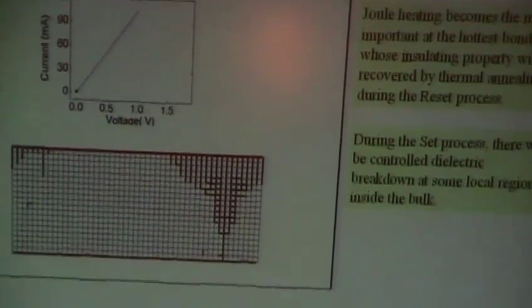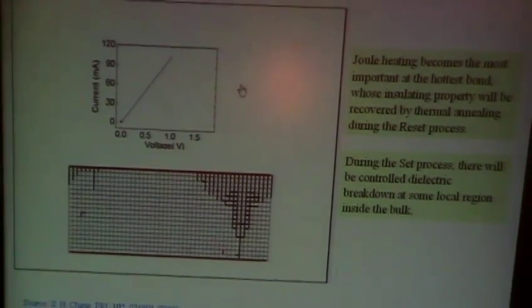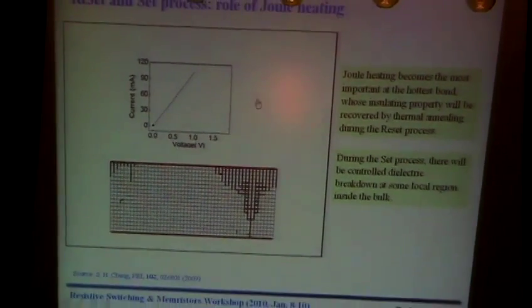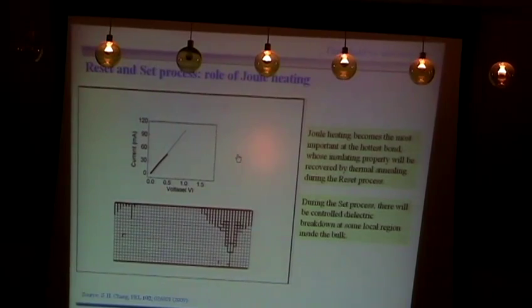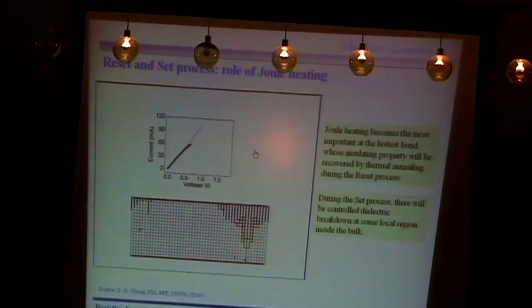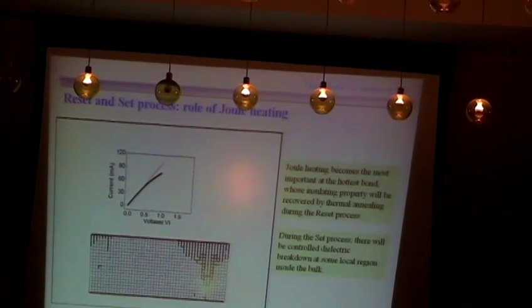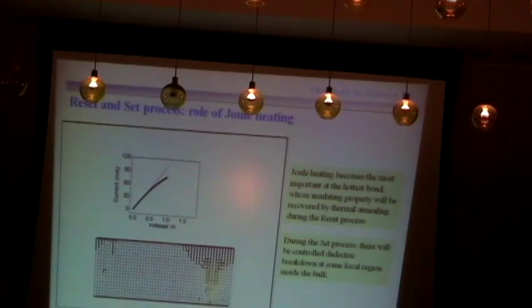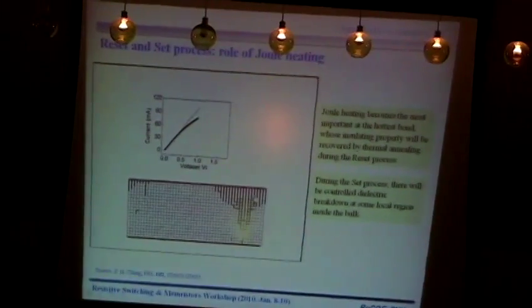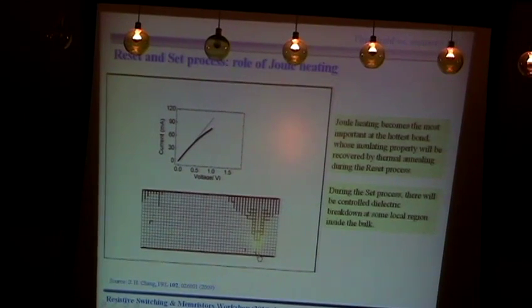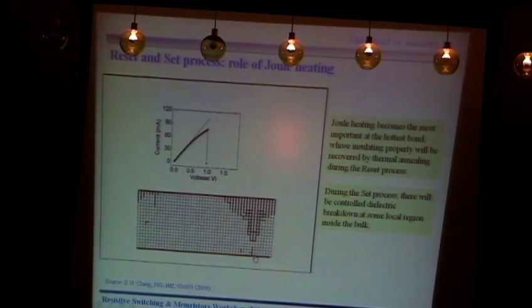So it is a kind of self-organized evolution process. That is the forming process. Then the reset and set process. Here we put in the Joule heating effect. As we put through more current, the temperature will rise. This region will get hotter than the other regions because most of the current goes through this hottest one. Then suddenly it will break down, so it will change into the high resistance state.